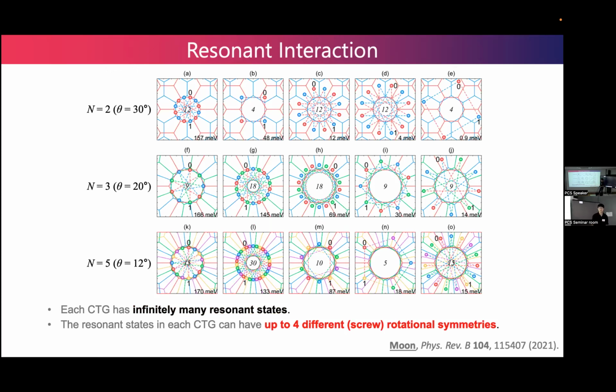Although this is a 12-fold rotational symmetry, it also has a 4-fold rotational symmetry in addition to the 12-fold rotational symmetry. So this is the coupling that I showed in the previous part. And this is also another resonant state. You can see the relative coordinates of red points are the same as the relative coordinates of blue points with respect to the blue hexagonal view and so on. And they are coupled by the reciprocal lattice vector of each layer. So these are the reciprocal lattice vectors of the red and blue layers, which means that these 4 states couple and make a 4-fold rotational symmetry. N equals 5 has 4 different rotational symmetries.